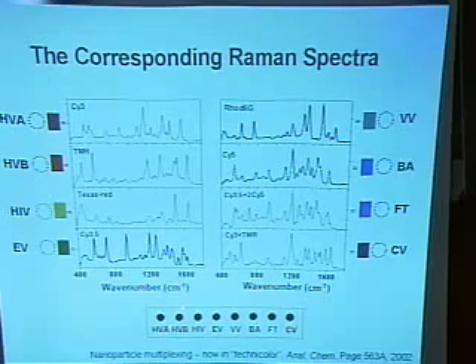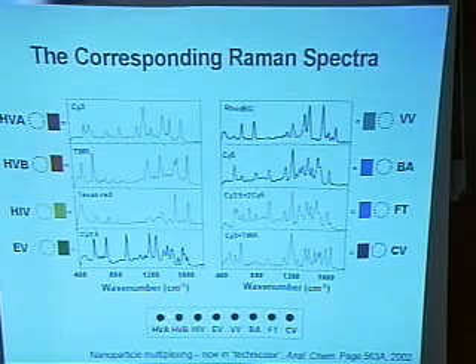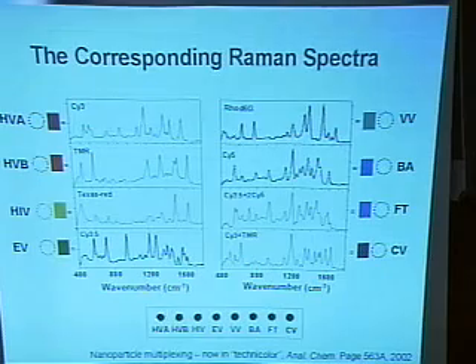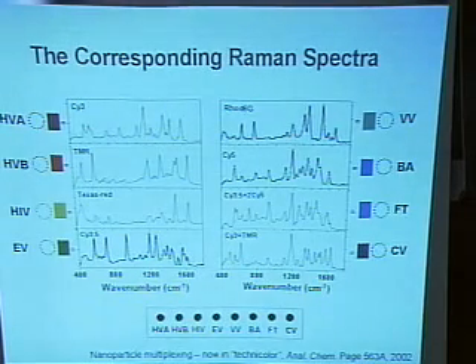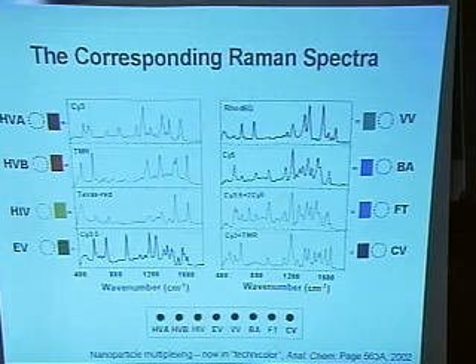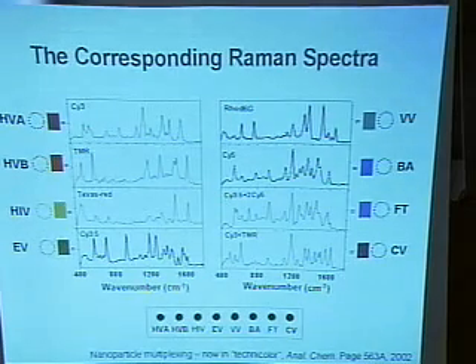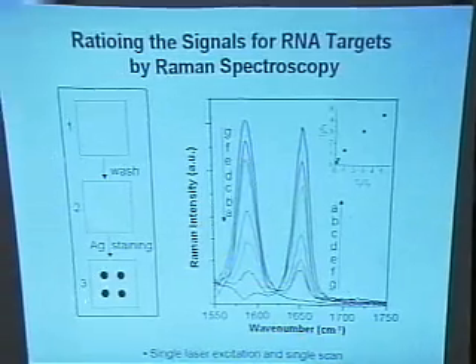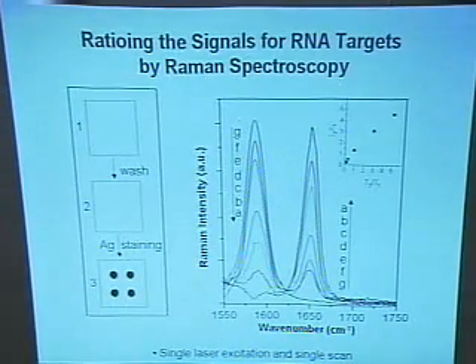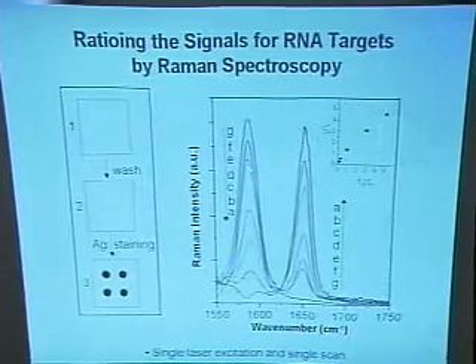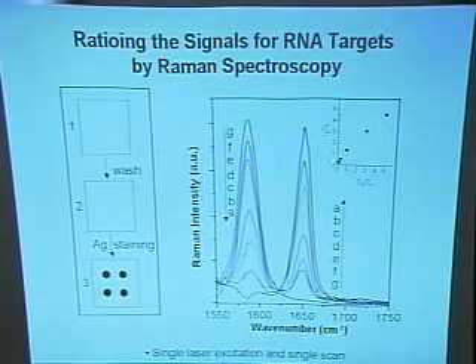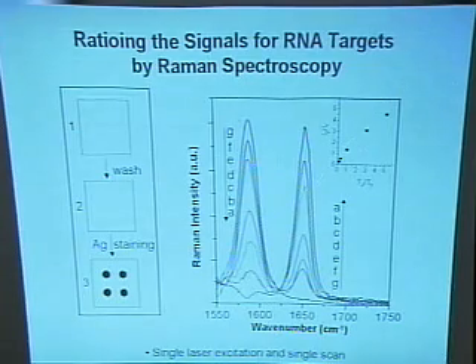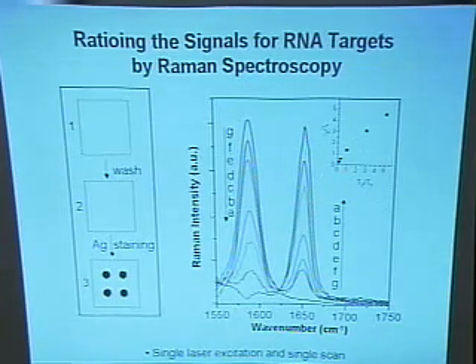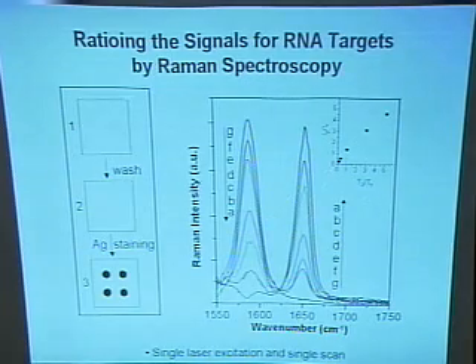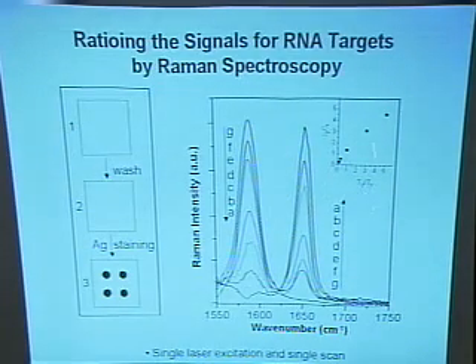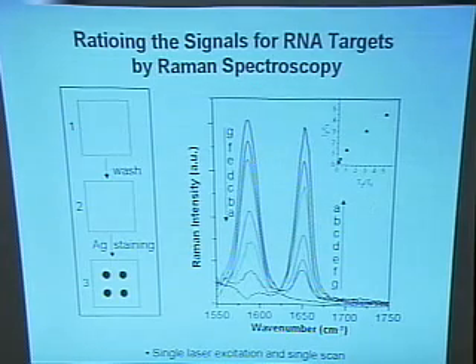So up to now, I talked about one spot having one target. Next I will show you one spot having two targets, where we do the ratioing. So this spot has two RNA targets. By changing the ratio, we can get the two peak intensities to change, with a nearly linear relationship between the ratio of the two targets and the two intensities.